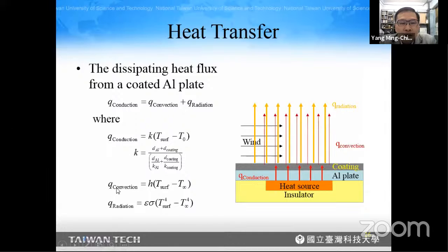For convection, the heat flux is equal to the heat transfer coefficient times the surface temperature minus the air temperature at infinite distance. And for radiation, it's the emissivity times the constant and the surface temperature to the fourth power minus the air temperature at infinity to the fourth power.